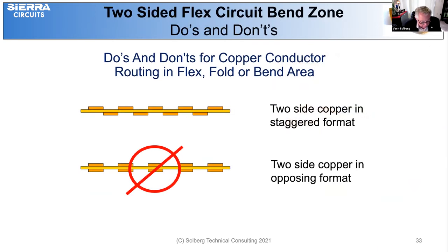For two-sided flex, multiple conductors are routed in the same direction on both surfaces of the flexible base material. The circuit paths on each side in the bend zone must be offset from the other to prevent stress cracking of the copper foil. When conductors are positioned directly opposite one another on opposing sides, flexibility is significantly reduced. Additionally, when the flexible circuit is installed in a product with a right-angle bend, the copper conductors on the outside of the bend will likely cause micro-cracks that can cause intermittent opens in the circuit during operation.